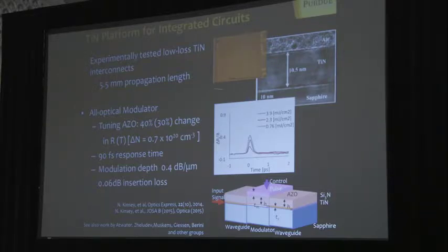It's beautiful work. Anyway, the first question to respond to was, if I would like to make an interconnect, basically a plasmonic waveguide out of titanium nitride, how would it compare to gold? And it turns out with titanium nitride, we could very easily make epitaxial, single crystal quality. You could see it, this is 10 nanometers thick. Unfortunately, maybe not that easy to see, but it is really single crystal quality. It's almost defect free, as opposed to gold. Gold, of course, is polycrystal.